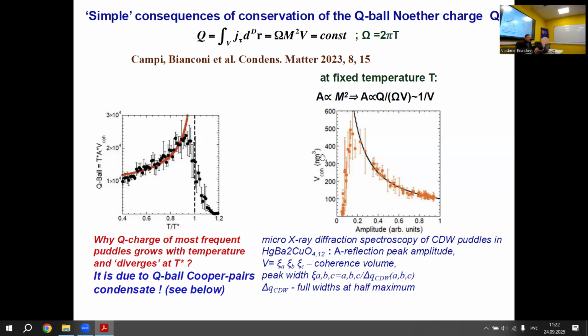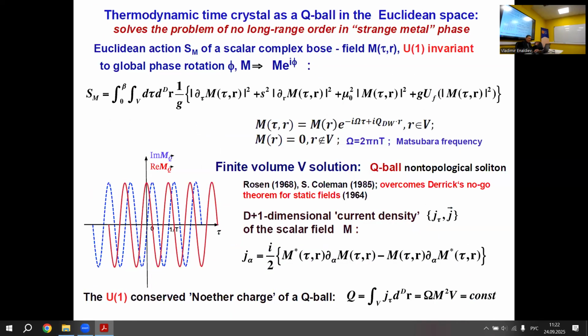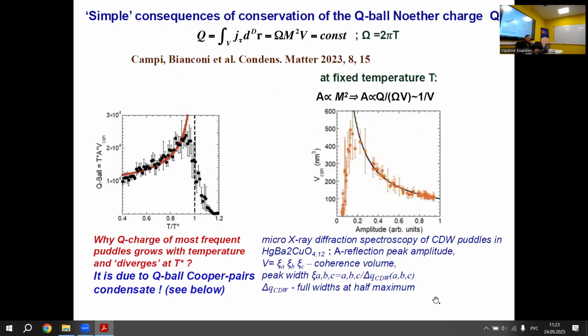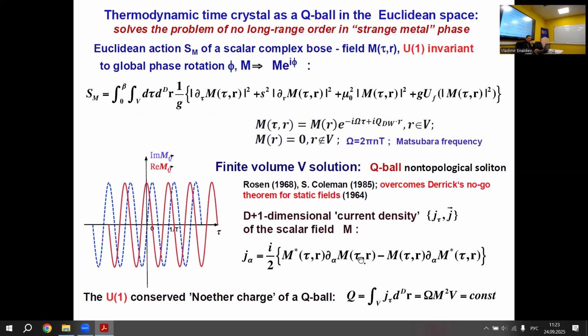And if you consider scattering of X-ray on the Q-balls, and that the amplitude is this m, then you see it's indeed so. And also, they finally compiled the product of the experimental points for different temperatures, different amplitudes, and different volumes, made this product together and found these points. And here it is the so-called T star temperature, below which the so-called strange metal in high TC cuprates appears. So some pseudogap, linear temperature dependence of the resistivity, and so on. And they indeed found, and this is the theoretical curve again, that it follows from this very simple relation.